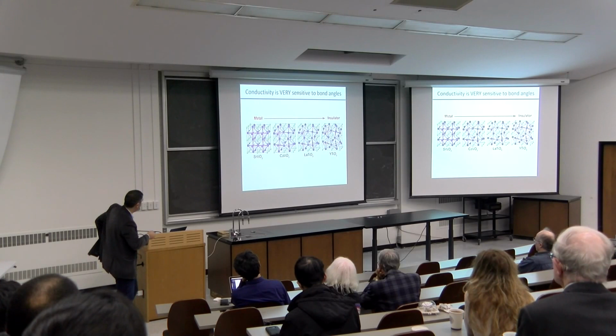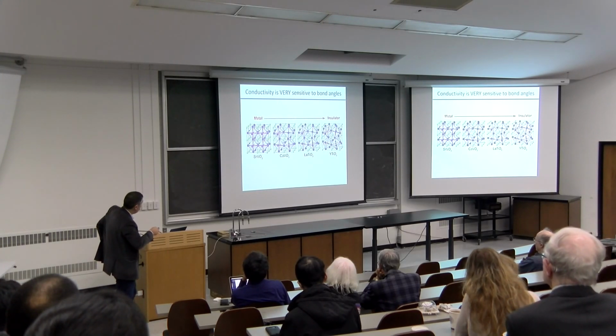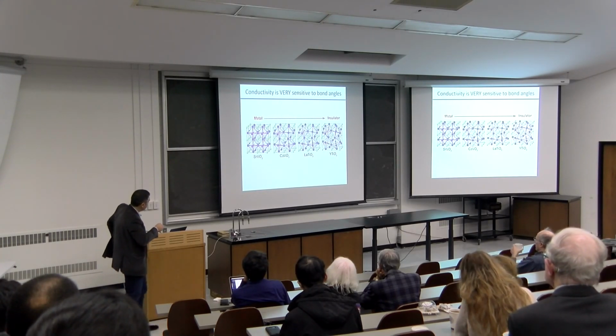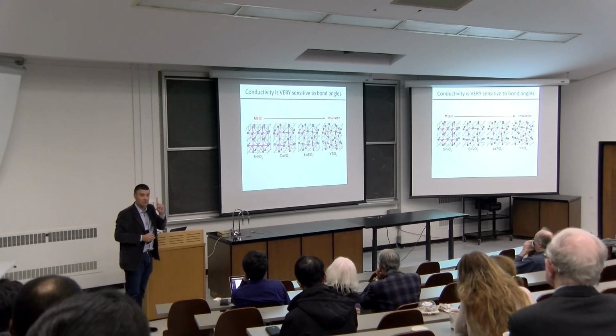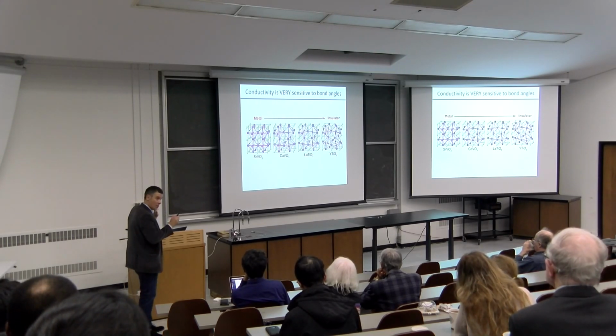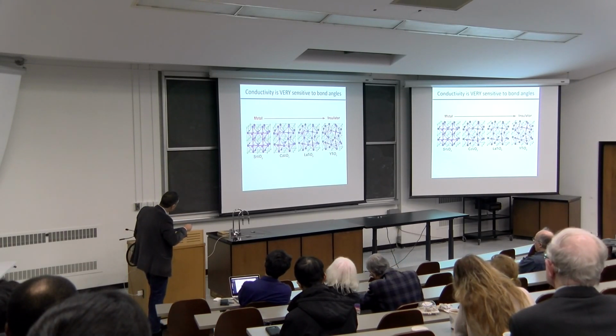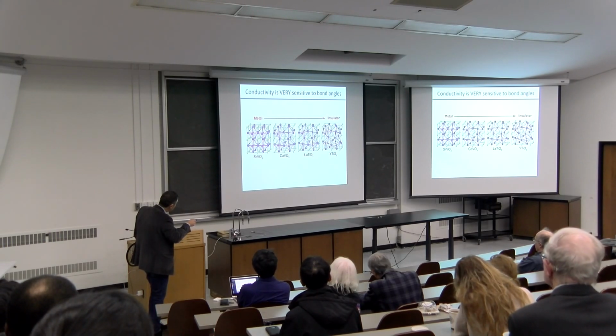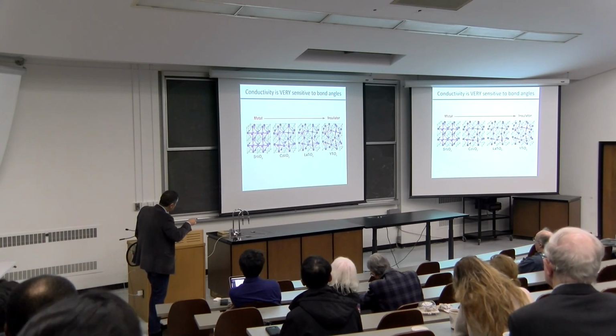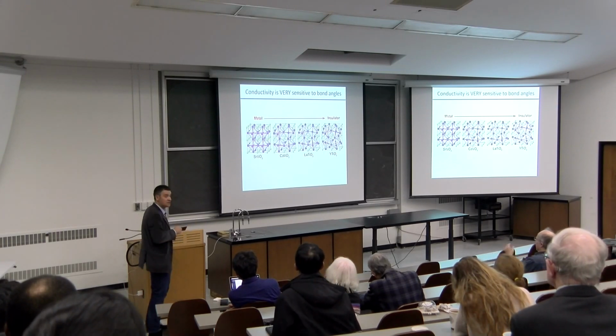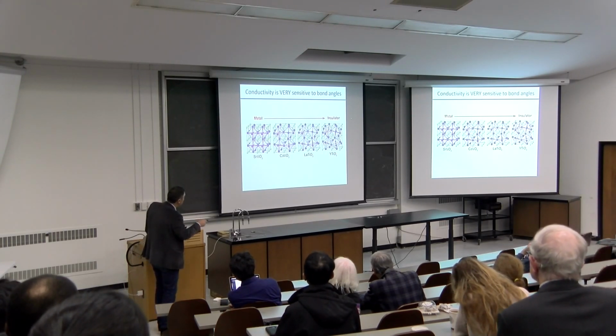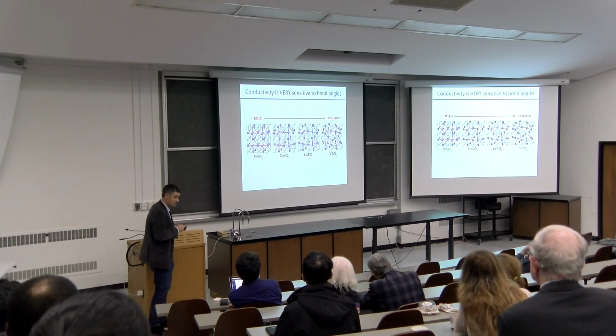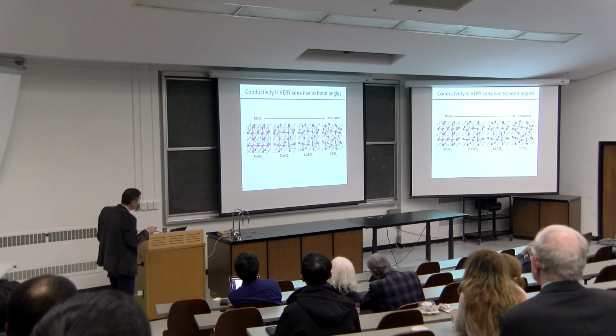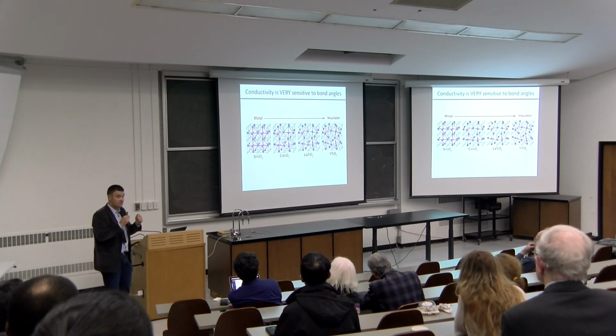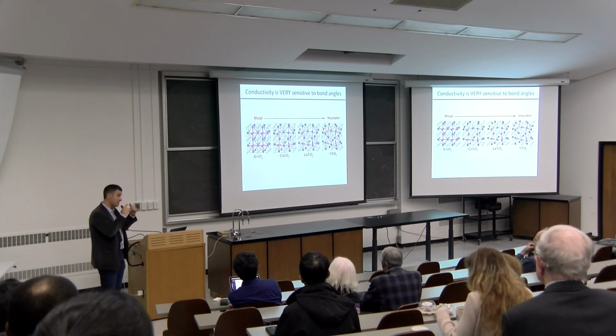So these are transition metal oxides, and these are basically all systems in which I only have one d electron close to the Fermi level. So these are seemingly the same, except that because of the structure, there's a bond angle here. Here's the transition metal, and here's the oxygen. This bond angle changes by a few degrees, and the conductivity goes from being a metal to an insulator and changes by many, many orders of magnitude. Okay? So this is an example, and in principle, what I would like to do is just simply go surgically onto one single bond and move it.